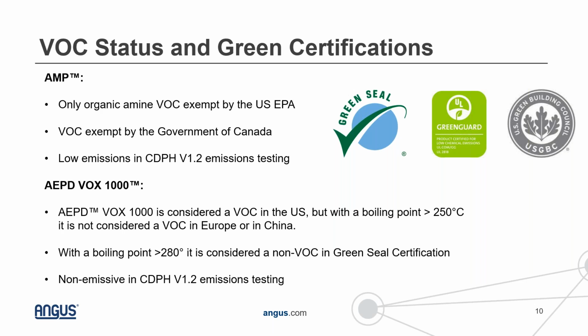AEPD VOX 1000. This is a material that, although it is considered a VOC in the US, because the boiling point of this material is over 250 degrees C, it's not considered a VOC in either Europe or in China. And because the boiling point is also above 280, it is not considered a VOC for Green Seal certification purposes. We also know that this material is non-emissive in emissions testing, which can be really advantageous for formulating coatings to meet certain green standards. We have data from this, not just from the California test, but there are equivalent tests that are run in Asia and also in Europe. And we know that it's non-emissive in all of these application tests.